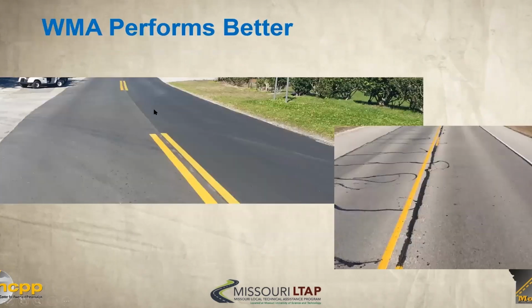If you look at this, I've seen this personally in instances where a test strip, you have hot mix and the warm mix. And so you can see the color difference between hot and warm, and that really lends more credibility to the fact that you've got higher volatilization and kind of the maltenes going up to heaven in the form of emissions, versus here with the warm mix at lower temperatures, more of the binder is left, which is going to translate to this next side over here, this other picture, where you have more cracking because you have less of the maltene fractions or the same fractions we use for asphalt rejuvenation, for instance.